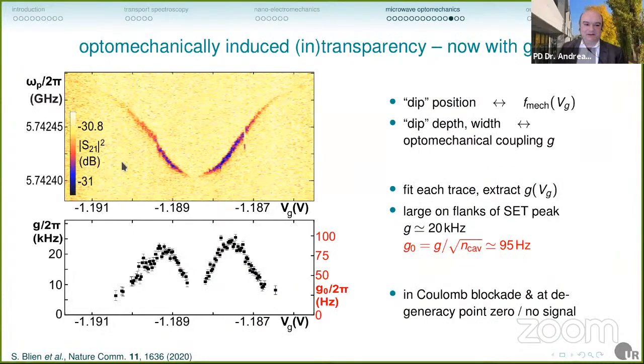And you can see that when we go across one Coulomb oscillation, we have an increasingly strong dip at the flank of the Coulomb blockade oscillation. At the center of the Coulomb oscillation, it shrinks back to nothing again. And on the other side, it comes up again and then disappears into Coulomb blockade. The position, so where it exactly is, that corresponds to the mechanical resonance frequency. That's not so interesting. But the dip depth, so the signal strength of this dip here, that corresponds to the optomechanical coupling. And so we can take a fit for each trace here and extract these coupling parameters. And you can see how it increases on the flank and then goes to 0, increases on the flank and then goes to 0 again, and reaches values up to nearly 100 hertz here.